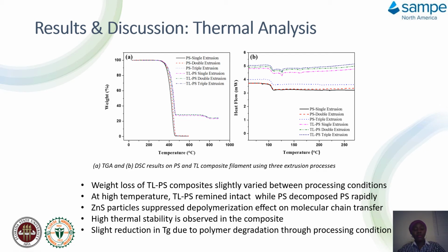For the composite, it shows there is a slight weight loss because the initial weight of the TL inclusion in the composite is 40 weight percent, but from the TGA result, it shows that it's about 30 weight percent, which means it's lesser than the weight percentage inputted in the beginning of the process.